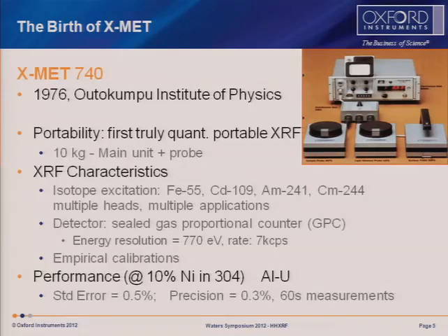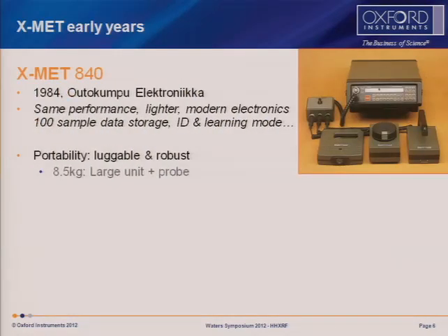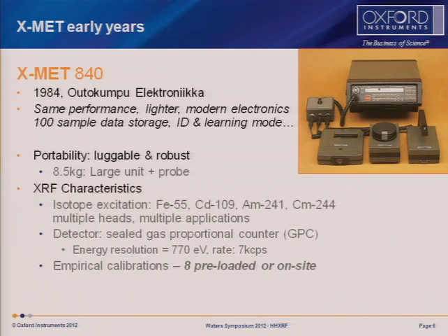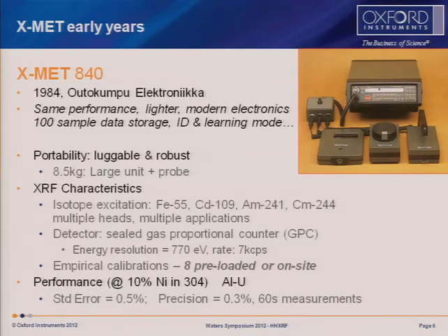Not a particularly convenient setup, as you see. It required a physicist generally to operate it. But it soon grew up, and by 1984, the 840 came along, still with a portable configuration like this, multiple heads for each different application, but now with electronics that could do much more, multi-channel analyzers with which you could do much more application. It weighed in total about 8.5 kilos, and in terms of its XRF characteristics, was the same as before, but look, modern electronics begin to kick in. You could actually load things and keep them on there. Your calibration didn't have to be made on the day. In terms of performance, the same fundamental performance was still available, so it wasn't changing technically at that stage.